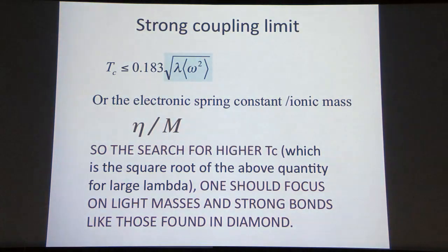So I'll just give you the bottom line on the latest work on trying to get the high temperature superconductors. I mentioned that the transition temperature goes like the square root of this lambda parameter times the phonons. It turns out that that's the same as an electronic spring constant that we can calculate that's very strong for strongly bonded materials divided by the mass of the atom. The square root of this gives you the transition temperature. So we're looking for things that have strong bonds and light masses.